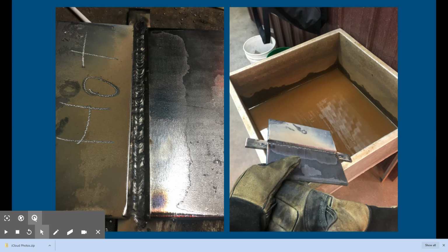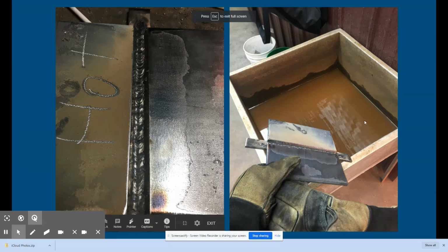You can use little temp guns. You can use a temperature-sensitive crayon, temp sticks. They're kind of expensive, but if you just get one that's 20 or 30 or 50 degrees lower than the maximum interpass temperature, you just rub it on there. If it melts, it's too hot, and you can let them cool down a little bit. But they recommend not quenching it. But again, it's A36 steel. It probably won't hurt it. So if a kid accidentally quenches theirs, don't make them throw it out. Just go ahead and test it.